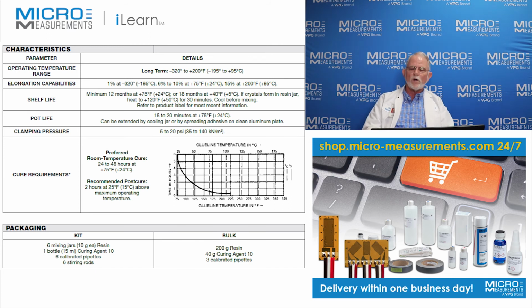And he said he used 20 pounds. And I said, 20 psi? He says, no, it's a 20-pound weight. And I asked him, over what square area? He says, well, it's one of your GT14s, which is nominally about 1/3 of a square inch. So he had 20 pounds of pressure on 1/3 of a square inch, so he's making 60 psi. And it clearly states in the instructions, 5 to 20 psi. He had overclamped it by about 3 times.